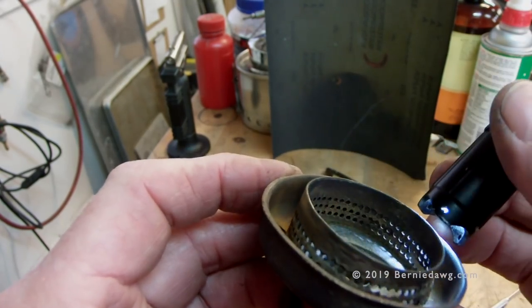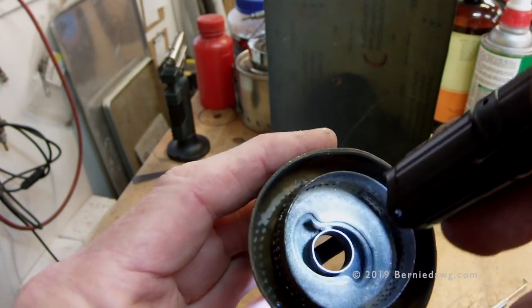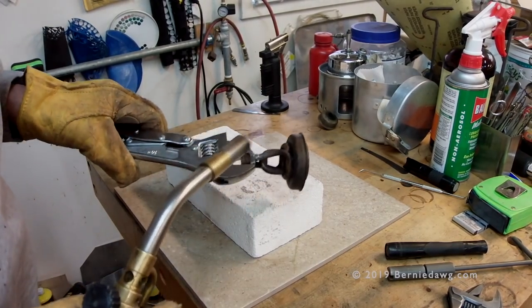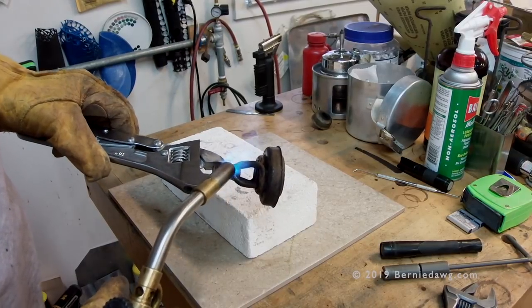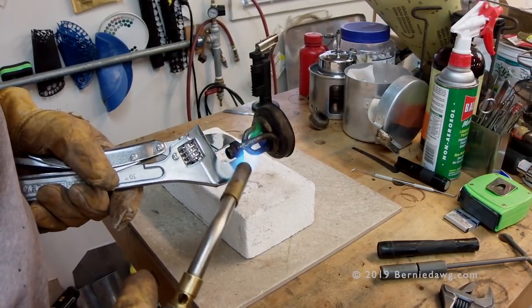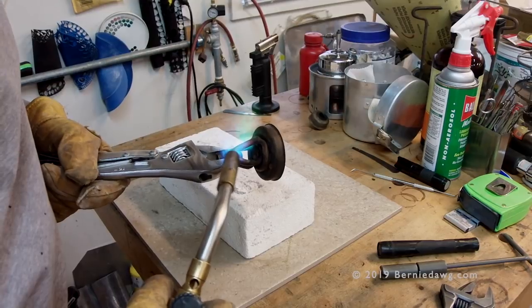I have to replace the ring — I'll remove the old one, make a new ring, and braze it in place. My first move was to remove the solder as much as I could by heating it up and flinging it off, or once it's liquid, scrubbing it off with a brass bristle brush, then using very fine glass bead blasting to remove the rest.